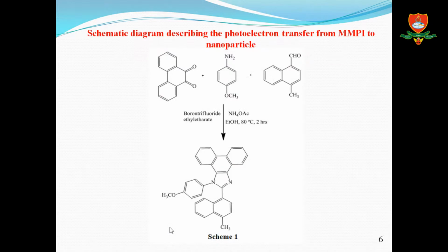The schematic representation gives the photoelectron transfer of nanoparticle, adding a mixture of 4-methyl, 1-naphthaldehyde, phenanthrene-9,10-dione, and 4-methoxyaniline in the presence of ammonium acetate with boron trifluoride ethyl etherate. The reaction mixture was stirred at 80 degrees centigrade for 2 hours. The reaction was monitored by TLC. The product was filtered and then dried.